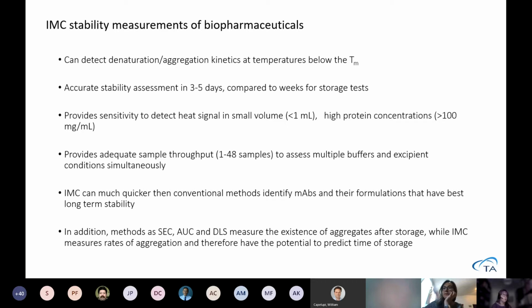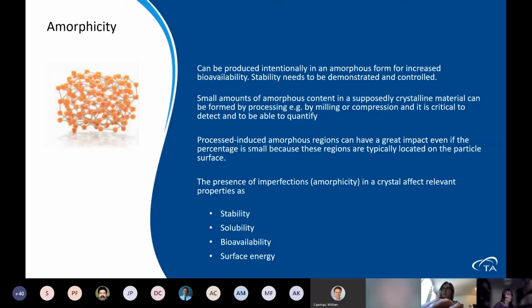You can get a higher sample throughput, so you can screen a lot of different buffers and excipient conditions simultaneously. And it is quicker than today's conventional methods to identify the formulations with the best long-term stability. In addition, as we mentioned, these other types of methods measure the existence of aggregates after storage, while we are measuring the rate with the microcalorimeter. So we have the potential to predict the time of storage. We don't need to wait till the process is finished. We can predict it during the process.